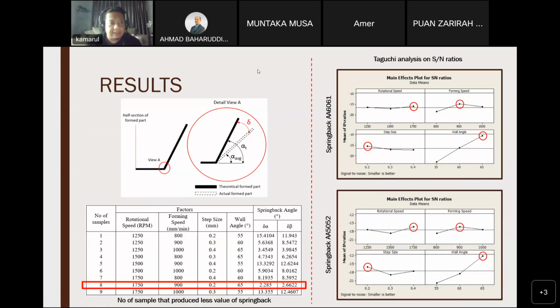Okay, the result. This is how to measure the spring back: after we find the average angle of spring back, the standard calculation is actual spring back minus design spring back. Based on the results, sample 8 produces very little spring back on both sides. The 6061 material is slightly different from the design angle, at 2.285 degrees. For the other side, the 5052 material produces 2.6622 degrees, slightly different from the 65 degree design angle.